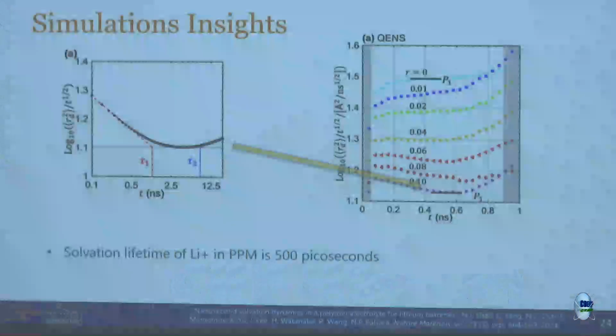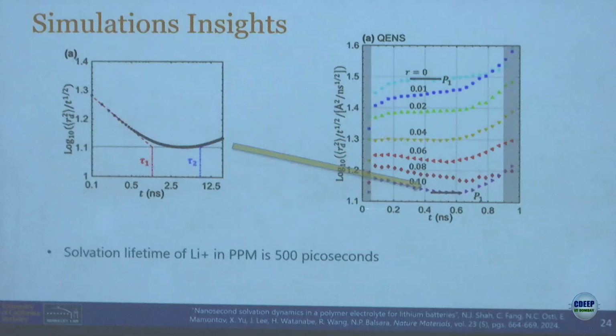We said that because of this picture, the solvation time, which was previously determined by 2D IR, can be determined if we just see how long the network survives. And in the polymer physics literature, it was known that this mean square displacement over t to the half would have this signature in reversibly crosslinked systems. And so we went to the simulation. This is Xiaofang, and we get the same thing that we saw experimentally. And from the simulations, we can tell that the solvation lifetime in our system is 500 picoseconds. And this is the first measure of solvation time that is not 1 picosecond, and we think it's correct.